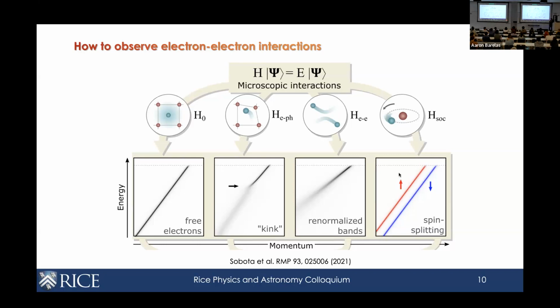So as a demonstration, here is a dispersion of free electrons, assuming no interaction. This is energy versus momentum, and this is your so-called band. If the electrons are interacting with some phonons, that will produce a so-called kink in this dispersion. There's an energy scale associated with this. The electron dispersion from this energy scale to the Fermi level is renormalized. You can see the slope is reduced, and there's a larger scattering beyond this point, right? So by measuring this quantity, we can get information about the interaction strength of the electrons and phonons, and at what temperature they onset, and so on and so forth.